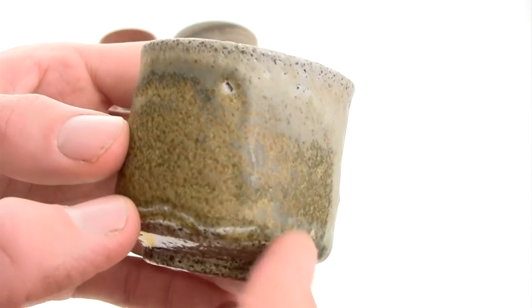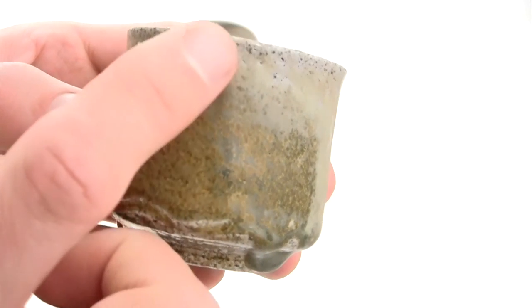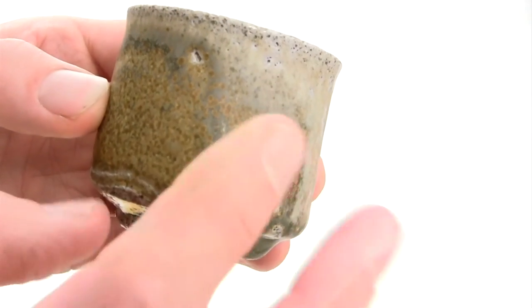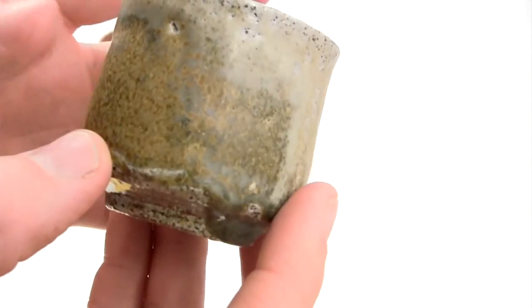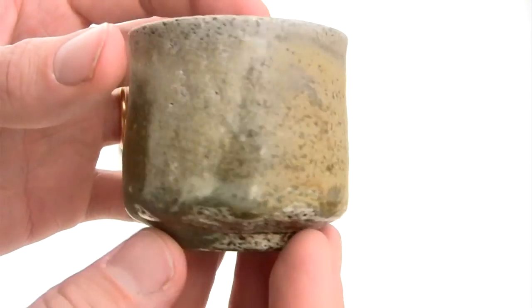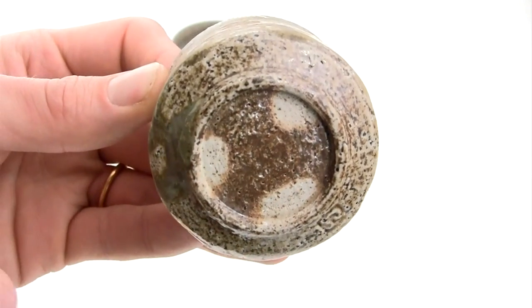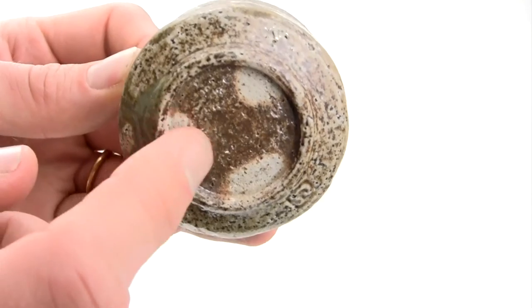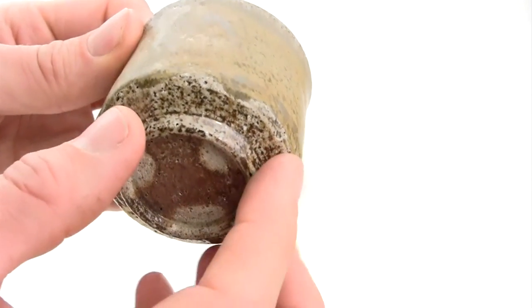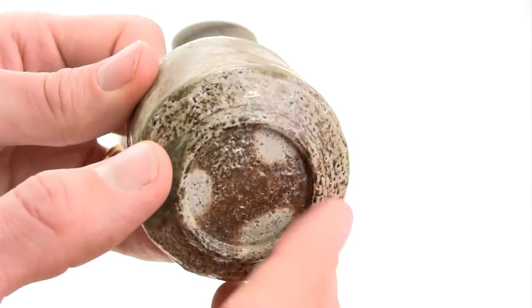If you look closely, you can see small crystals created during the cooling of the firing, at about a thousand degrees Celsius or so. This pot was only gray or grayish, and you can see that underneath here. But these crystals started to evolve as oxygen entered the kiln, turning the crystals not gray but yellow — goldenly green. It's been fired on three wadding balls, which is just a very refractory clay rolled into balls and put on the feet here and on the shelf in the kiln. Because in a salt firing, every piece of clay becomes sticky and glazed, so you'd have a hard time removing the pot without waddings of some sort.